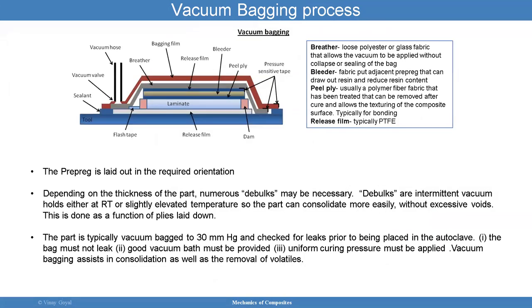The vacuum bagging process, you have the breather, which is a loose polyester or glass fabric, and that allows the vacuum to be applied without collapse or sealing the bag. So I'm pointing right now to the breather here, that one right there in gray. The bleeder, which is right here, right on top of there. So you have the breather, the release film, and then you have the bleeder.